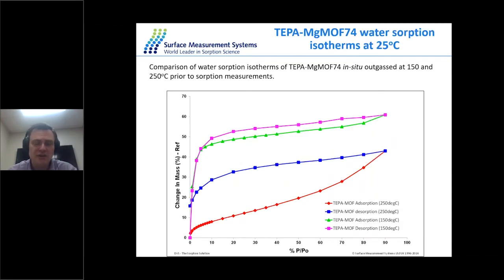Now, we also functionalized this MOF with tetraethylenepentamine in order to increase sites for CO2 adsorption. And what we can see, again, two striking differences. For each experiment, a fresh sample was used. So for the one outgassed at 150 degrees, adsorption in green, desorption in pink; outgassed at 250, adsorption in red, desorption in blue. What you can see, first, is the massive difference in adsorption capacities.